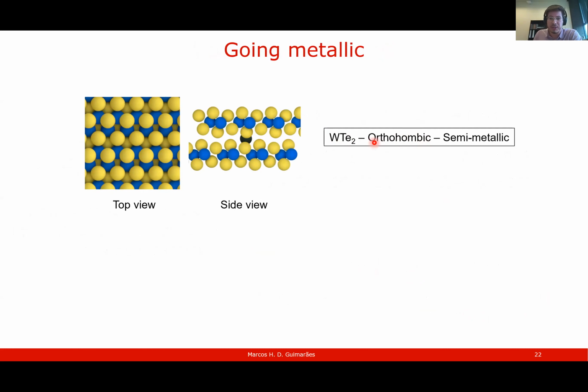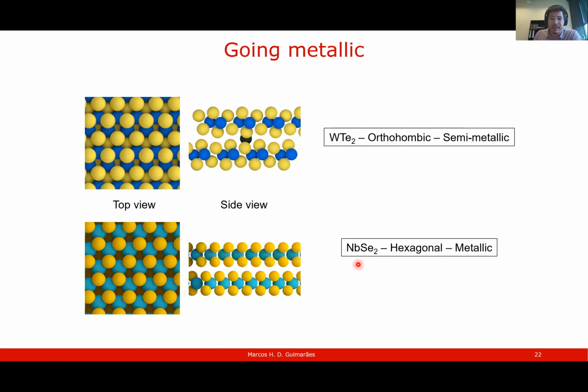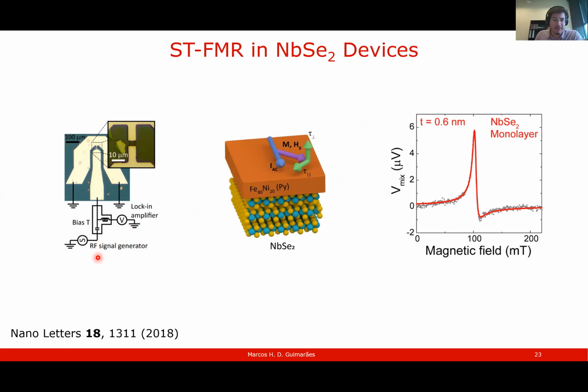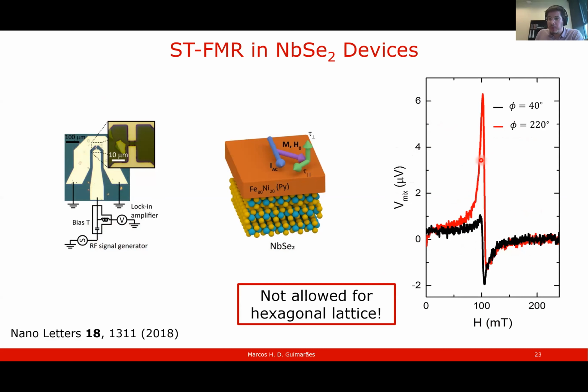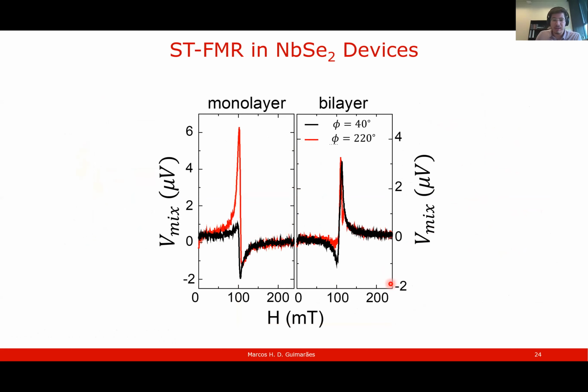So we leave tungsten ditelluride, which is a low symmetry system and semi-metal, and we go to niobium diselenide, which is hexagonal and metallic. It also has a higher spin-orbit coupling, in addition to the higher conductivity. So we played the same trick. Now STFMR on niobium diselenide permalloy, measuring the STFMR curve, and down to a monolayer of niobium diselenide, we see a strong spin-orbit torque response. However, if we reverse the magnetization direction, you can see here that the curves are very different. But this is actually not allowed for a hexagonal lattice. So what's going on there? So we add one more layer, and you can see that if we do the same thing for a bilayer device, the curves are a little bit more similar.